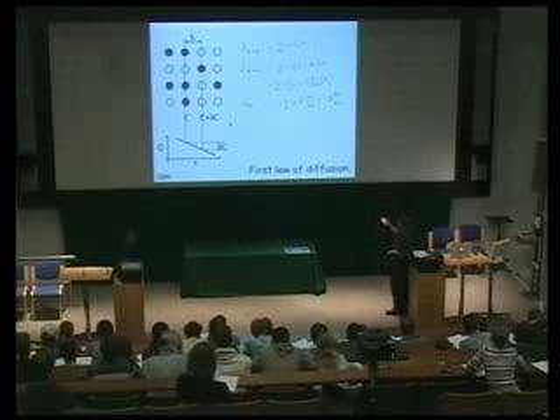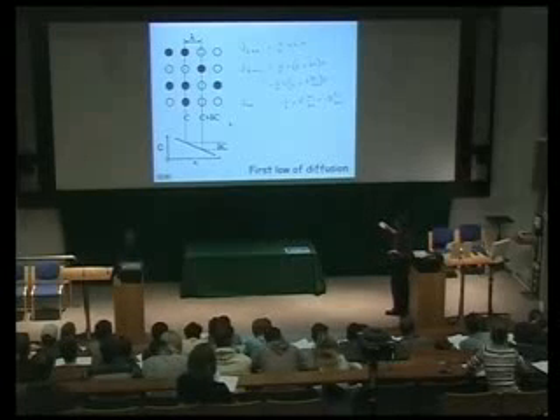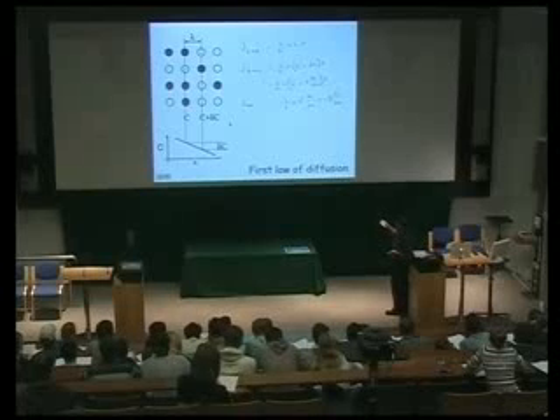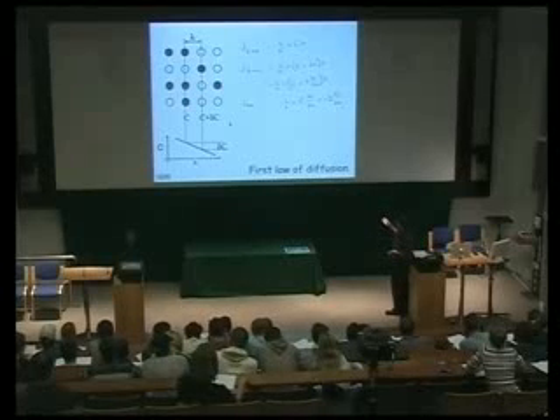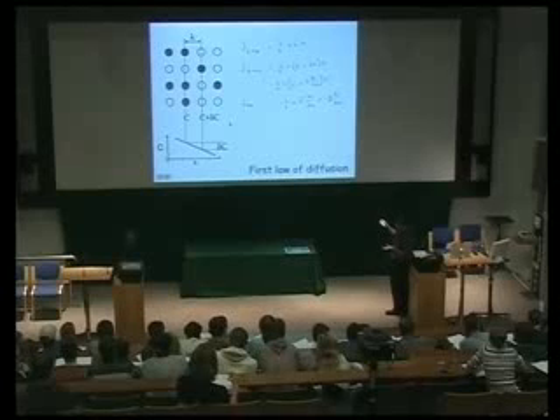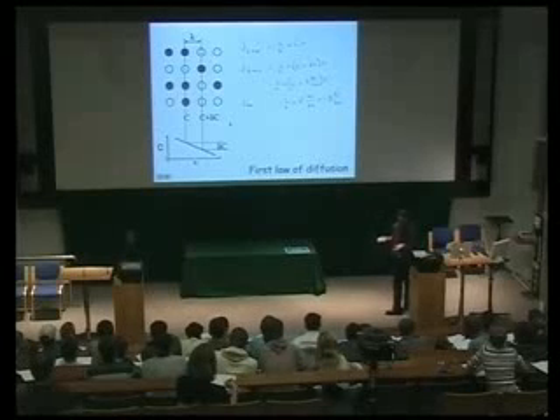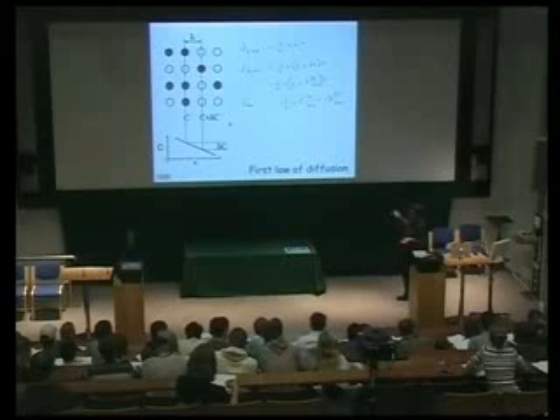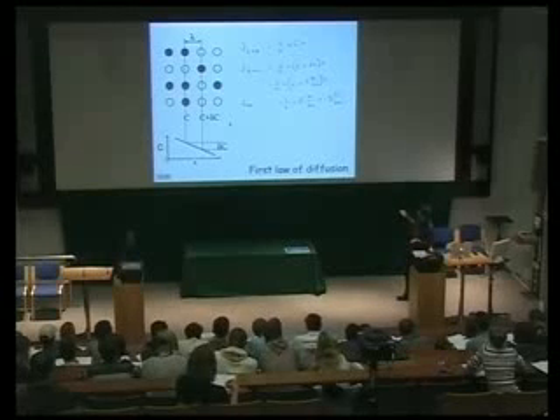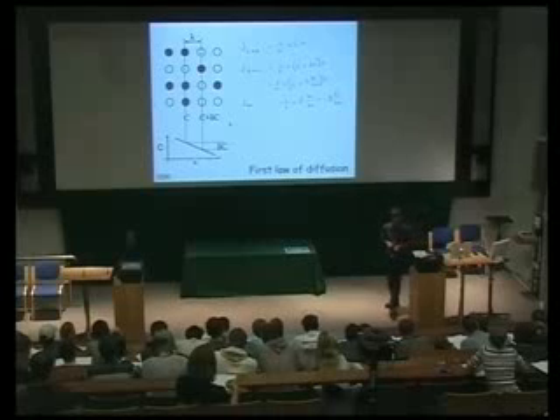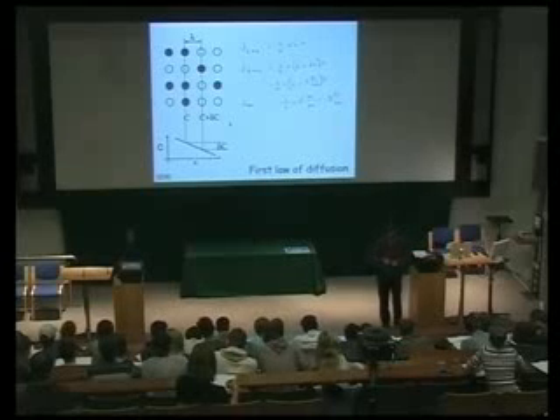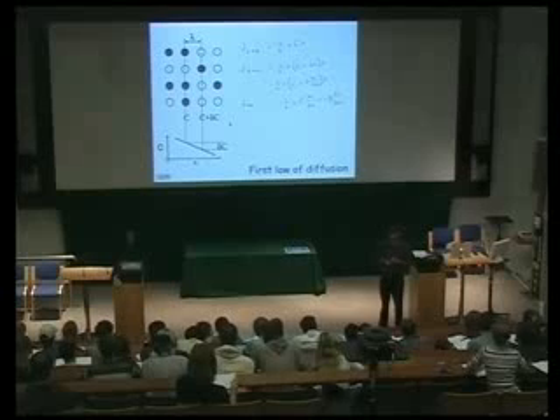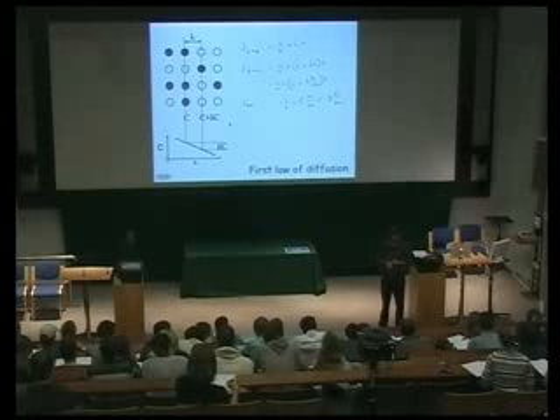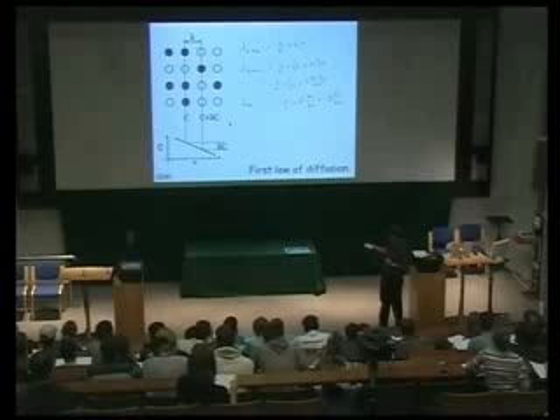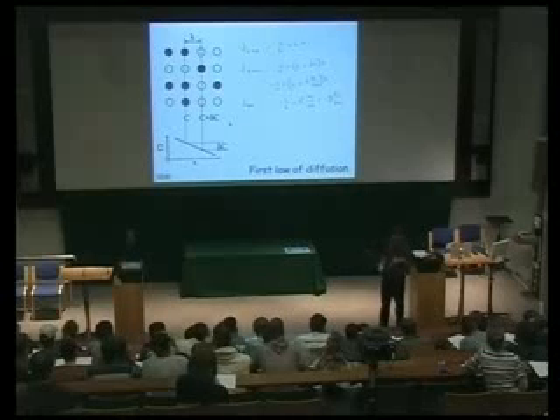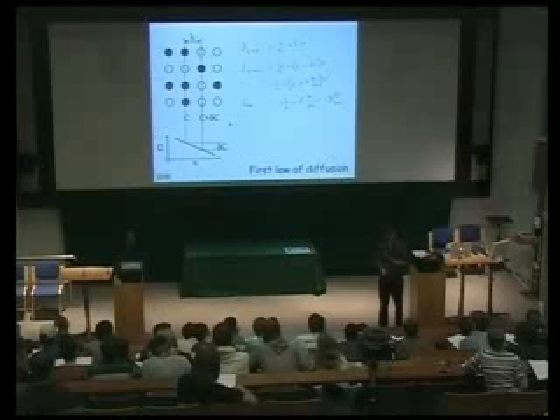So if I now take the difference between these 2, I get a relationship like this, where I'm absorbing all of these terms into this parameter d, which we call the diffusion coefficient. What you get is that the net flux is proportional to minus the diffusion coefficient times the gradient. Now, notice that there is a minus sign there, okay? And that's simply because the gradient here is negative, so the flux is happening down that gradient.